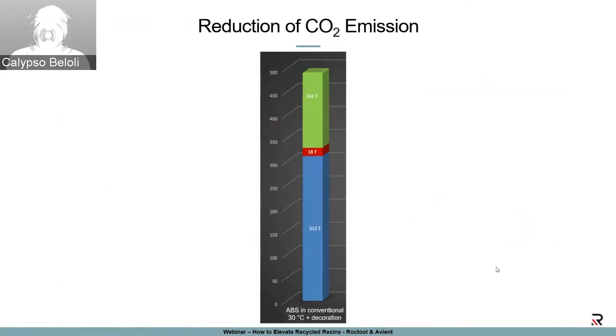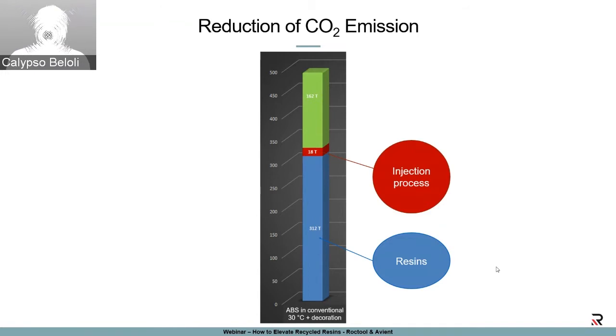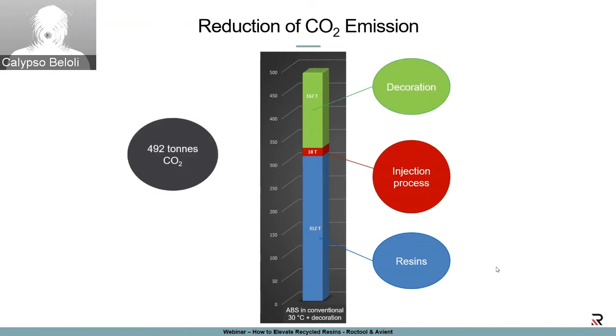So the first case is ABS in conventional, 30°C, with decoration in order to obtain a very good surface aspect. So in this case, you will have in blue the resin, in red the injection process, and in green the decoration. So to do 1 million parts with this mold, you will use 492 tons of CO2.